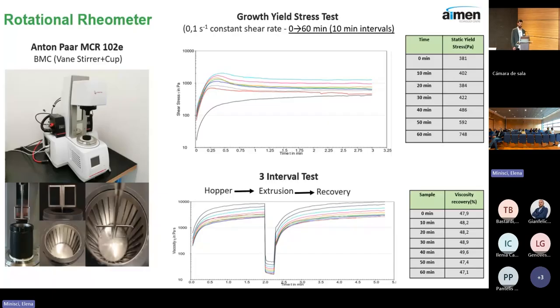First, we apply a low shear rate, which is when, for example, the cement is before extrusion, for example, in the hopper. In the second interval, we apply a high shear rate. In our case, we measured the shear rate of our small printer, the Delta One, in order to extrapolate the same conditions, and we measure the decrease of the viscosity. And in the third interval, we apply again a low shear rate, and we measure the viscosity recovery, which is related to the buildability and the properties after deposition.